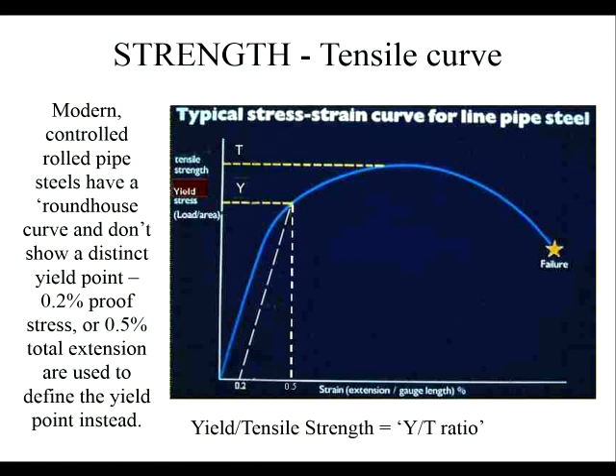The other thing you'll notice is that the yield stress, which is defined in this case by a constant strain offset, so here's the elastic part of the curve. You take a 0.2% strain, draw a line parallel to that, and see where it crosses the curve. That's a way of getting an unequivocal, easy to define yield stress. It's difficult to decide where this diverges from the linear portion, so that's why we use that. Anyway, this yield stress is much closer to the ultimate tensile stress.